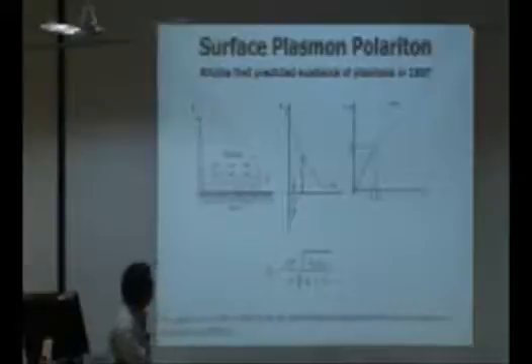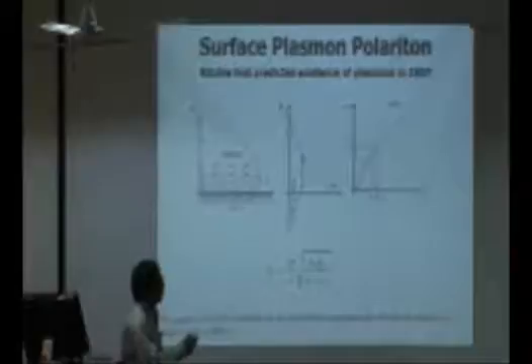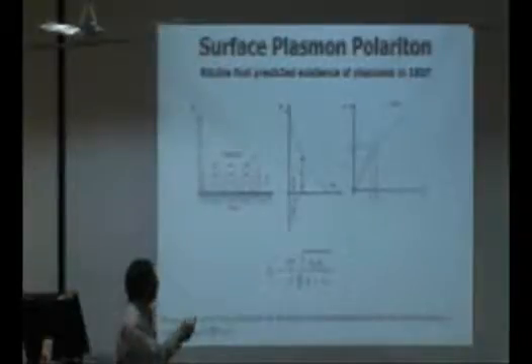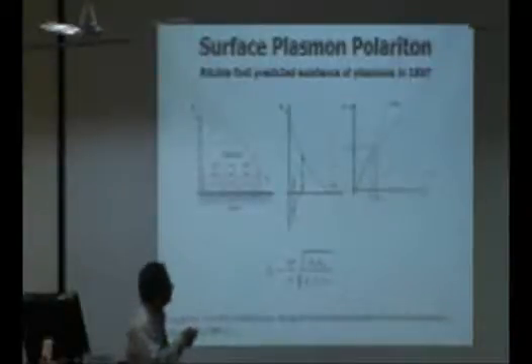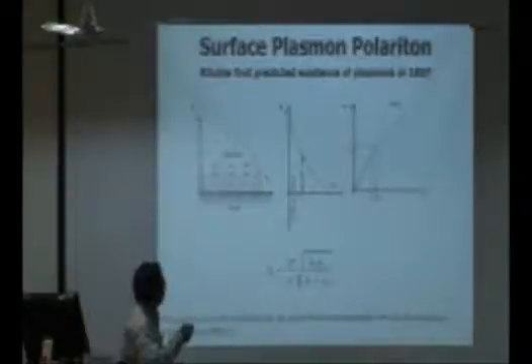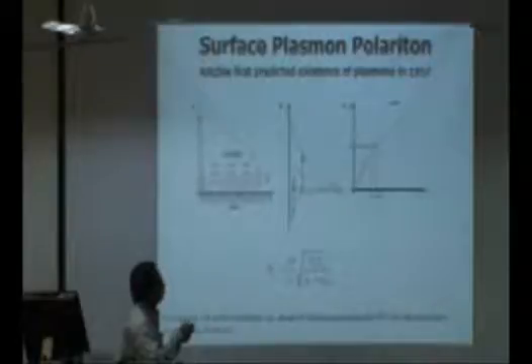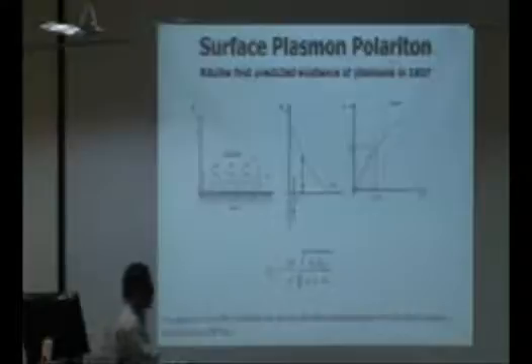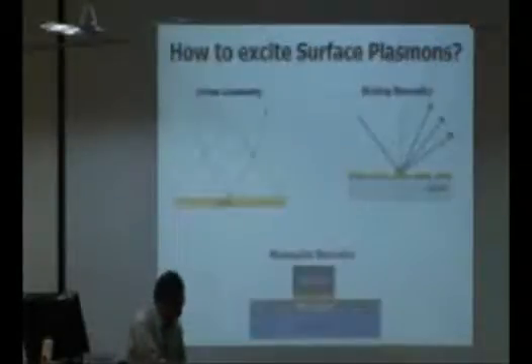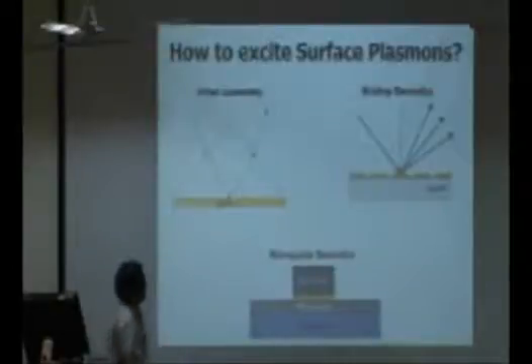So this charge density wave, or the surface plasmon polariton wave, has a dispersion relation given by this, which in comparison with the photon dispersion shows that there is a momentum mismatch between light and the plasmon mode at the interface. So this shows that for a given frequency of light, it's difficult to excite a plasmon mode at the interface. So now the question is, how do we overcome this problem and excite the plasmons using light? Okay. There are three different techniques which are generally used in the literature.